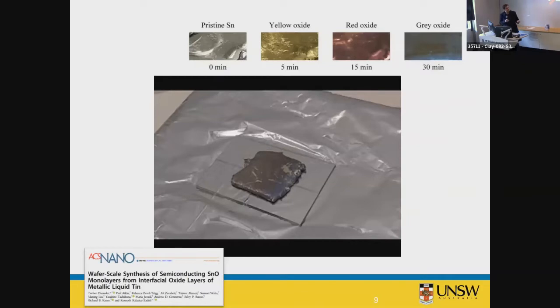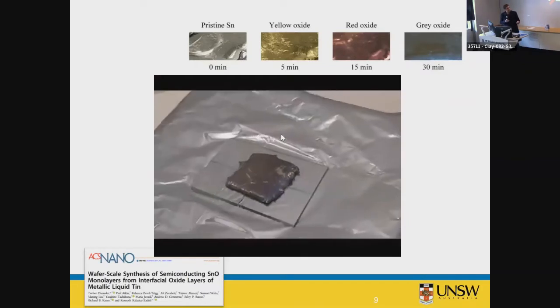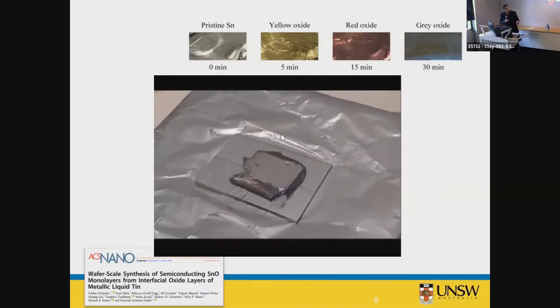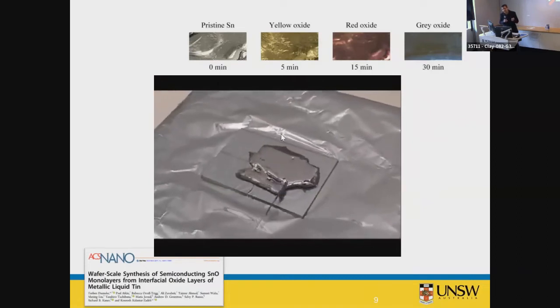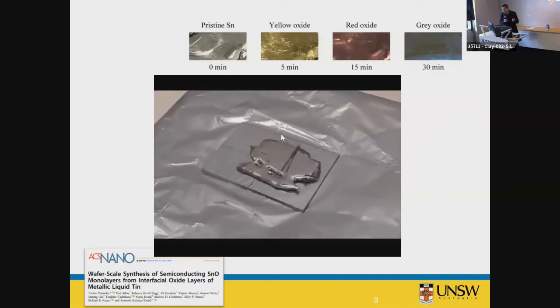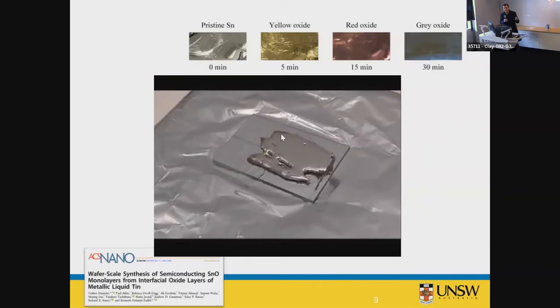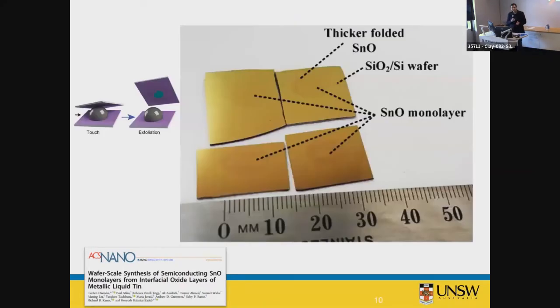This is tin, and as you see, this is more than two-dimensional because tin is not self-limiting. It becomes thicker and thicker in time, but you can take a piece of glass and remove the oxide from the surface. Imagine if it's gallium, it's self-limiting, becomes two-dimensional. Of course, you cannot see in this video. Now, for oxide of tin, we reduce the oxygen, make the film similarly. Self-limiting, if you bring the ambient oxygen from 21% of the room environment to only 1%, it becomes self-limiting. Then you bring a substrate here.